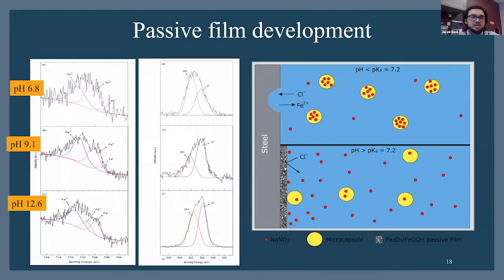As well as to wrap this whole idea up, we have XPS results showing the formation of our passive oxide films. So on the left here is our XPS spectra for iron. In our lower pH, we find that our Fe3+ is lower than our Fe2+ peaks in the deconvolution, showing that there is most likely corrosion occurring, with the formation of iron chlorides and dissolution. However, at the higher pH, the ratio of our Fe3+ to Fe2+ is much higher, and because of the presence of nitrites, that can evidence the formation of the passive oxyhydroxide layer, as well as the Fe2O3 or Fe3O4, the stable ferric oxide layers.